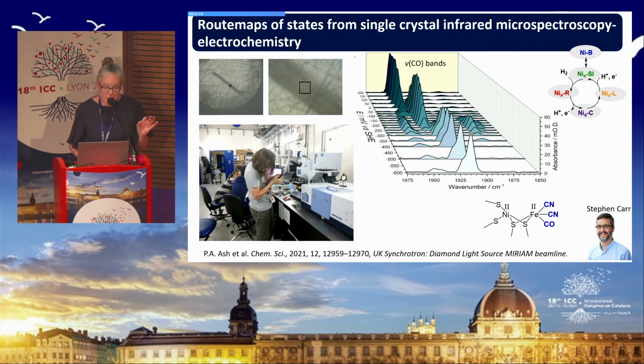So we were doing some different experiments on the infrared microspectroscopy beamline at the UK synchrotron Diamond Light Source. And while we were there, we had some crystals of hydrogenase that Stephen Carr, who's a senior research fellow and protein crystallographer within my group, had for X-ray diffraction studies on hydrogenase. And a brilliant postdoc in my group at the time, Philip Ash, who's now a lecturer at the University of Leicester in the UK, said, why don't we try putting some of these crystals of hydrogenase onto an electrode and applying a potential and seeing whether we can actually manipulate the crystals electrochemically. And it could have gone wrong for lots of reasons, but it actually worked absolutely brilliantly.